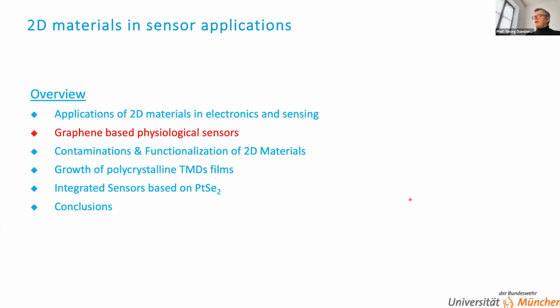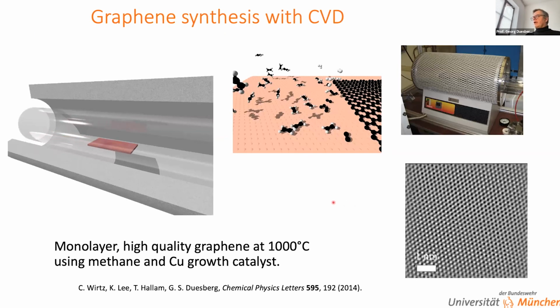So let's have a quick look at graphene and physiological sensors. And what I've been using, just as a brief introduction, is monolayer high quality CVD graphene. Even though I say high quality, it's actually not the highest quality. It was high quality about 10 years ago. But it's, let's say, standard good-ish material with mobilities around 1,000, which we grow in tube furnaces on copper. And if you look at the TEM, we end up with nicely crystalline material.